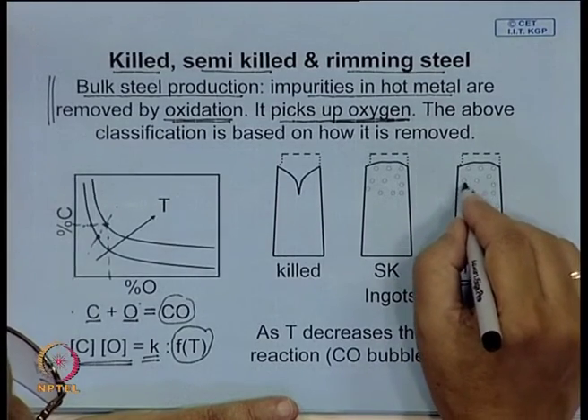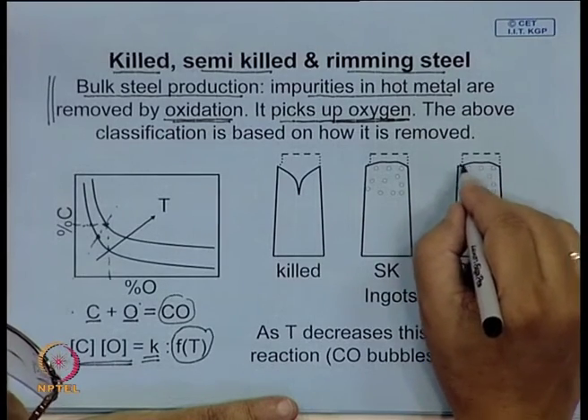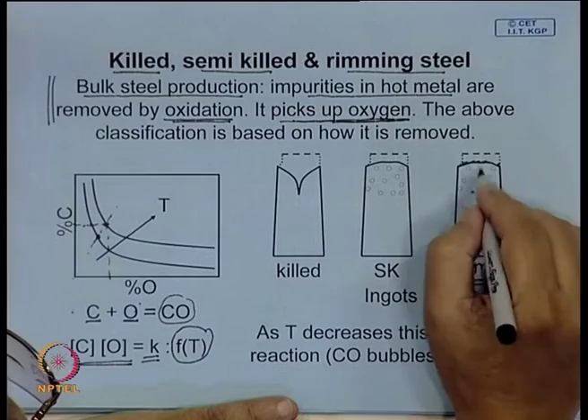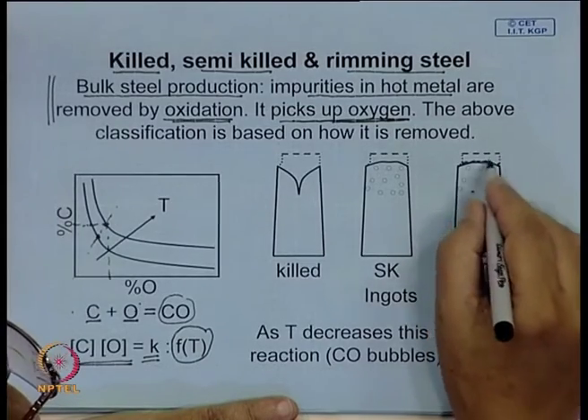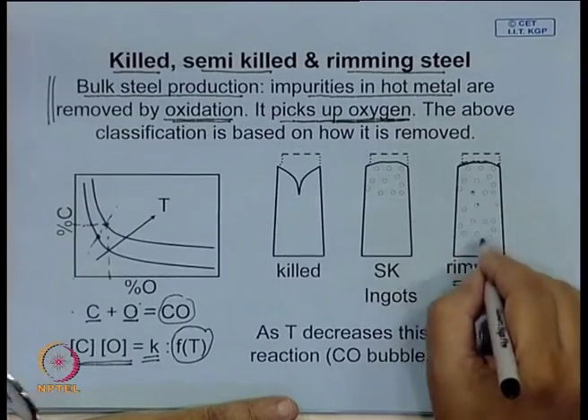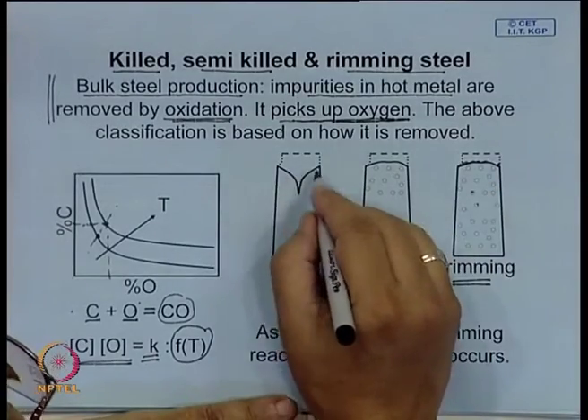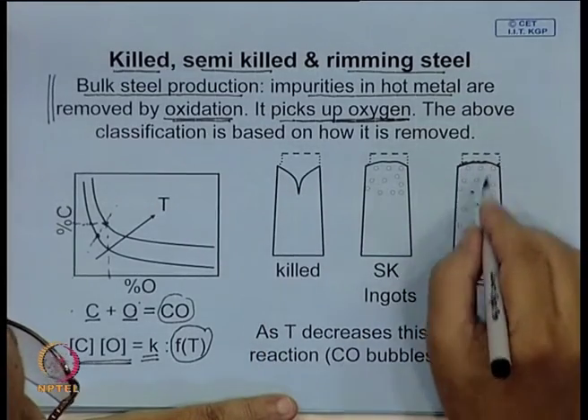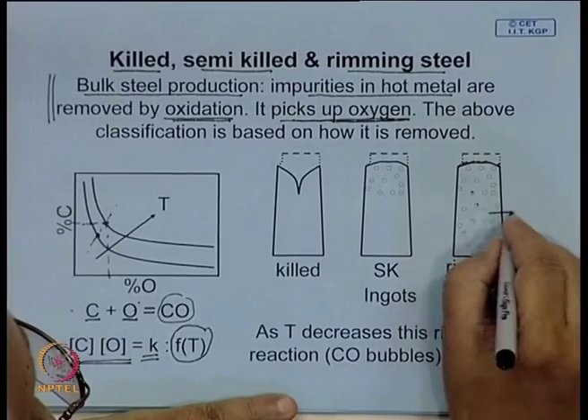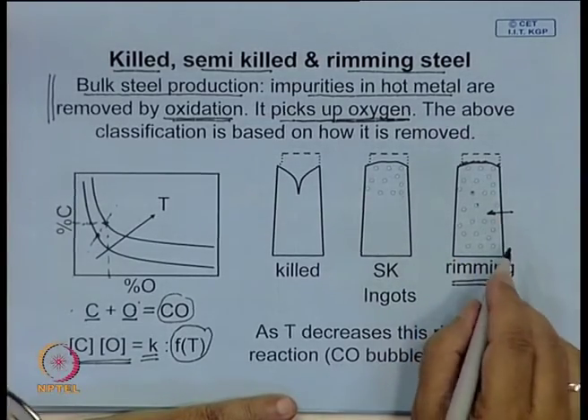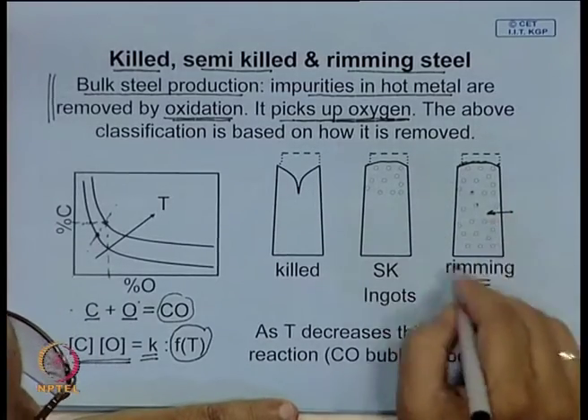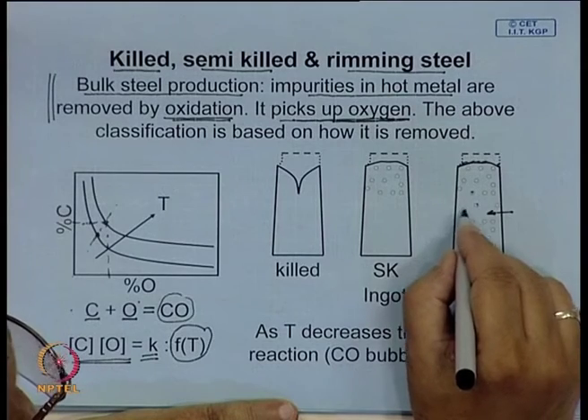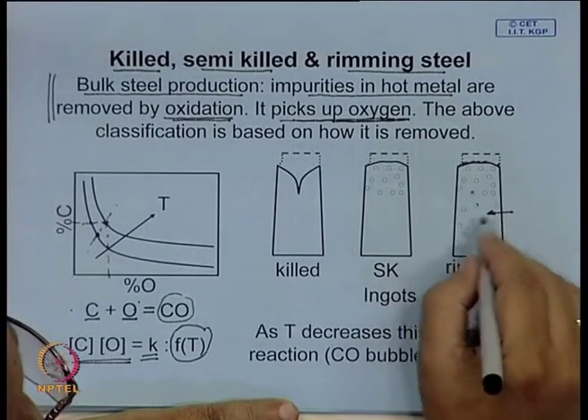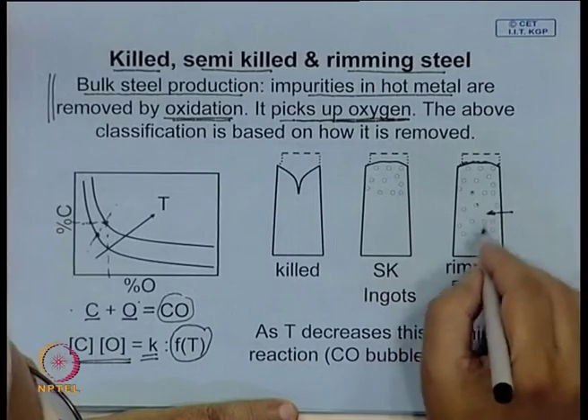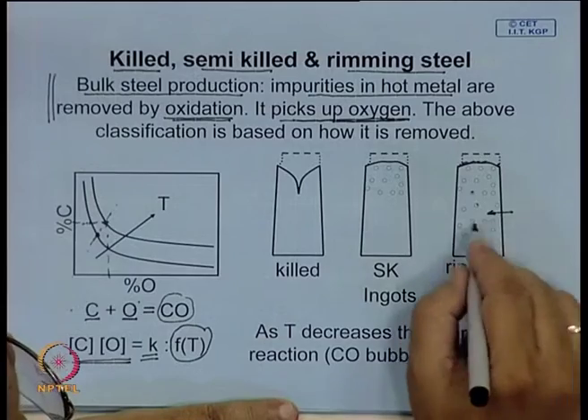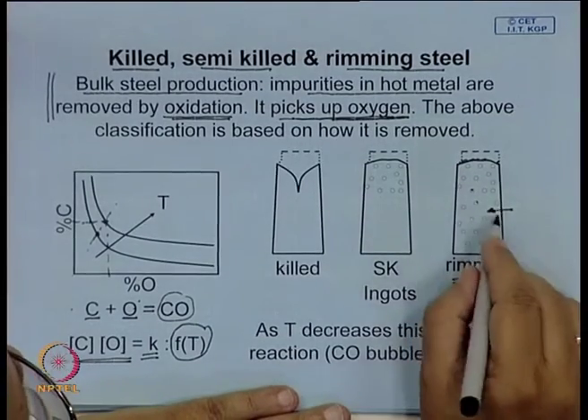Some of the CO bubbles are not able to escape, because if it forms a crust, they will not be able to escape, and in that case you have a steel which is full of CO bubbles and it compensates this shrinkage cavity. It has one advantage: you have higher yield. But it has a problem: you have some amount of dissolved oxygen in the steel and oxygen makes the steel brittle. So, rimming steel, although during subsequent rolling these pores seal up, because of some amount of soluble oxygen in the steel it has relatively poor ductility and a higher transition temperature.